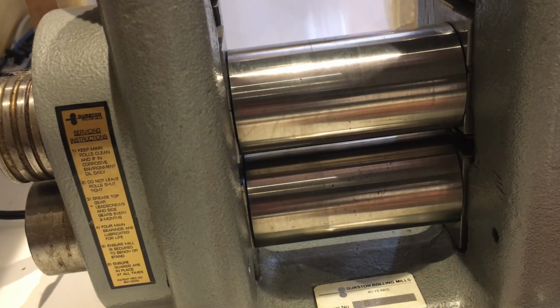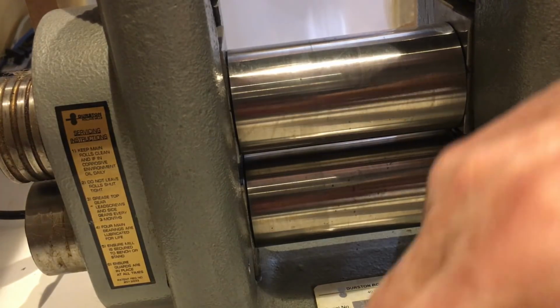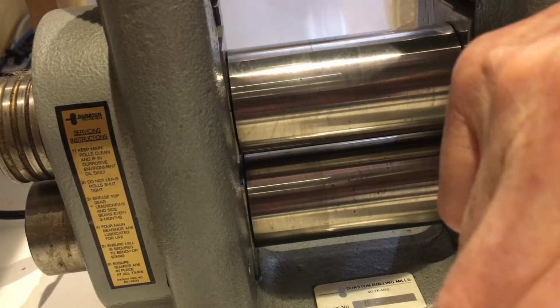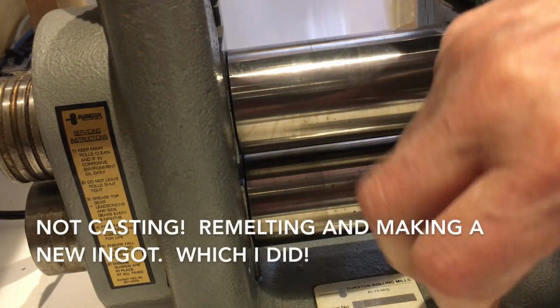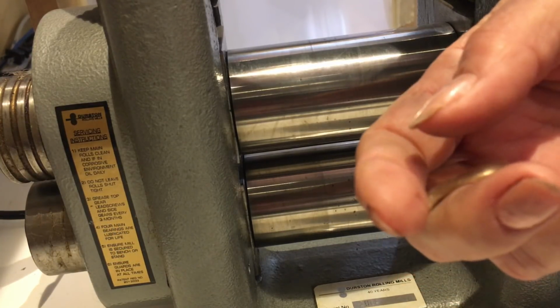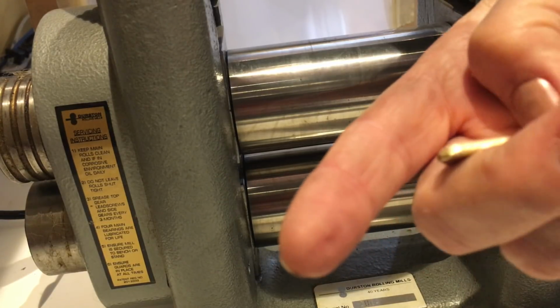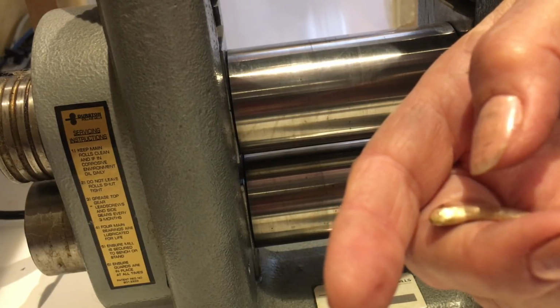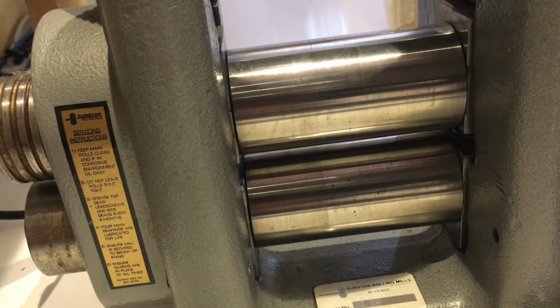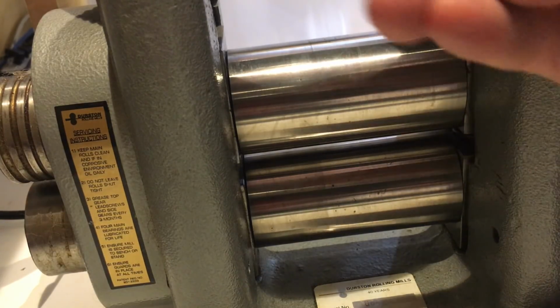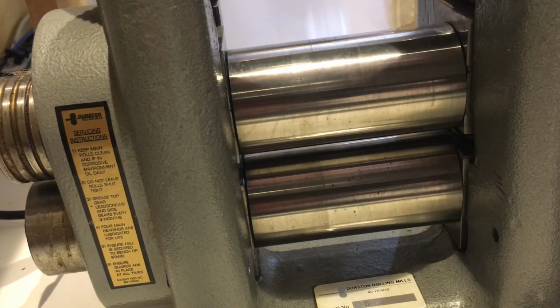If you get cracking and flaking, that could be because your metal ingot was too cold when you poured it in, or you have too much old material in there, or it was contaminated. So that probably will involve you recasting or sending it out to a refiner, especially if it's contaminated. If you've got one side that's thinner than the other, that usually means that your rollers are not even, so you need to adjust those. So those are some things to look out for when making sheet metal. So off to annealing again, and then rolling, and then annealing, and then rolling, and annealing, and time consuming.